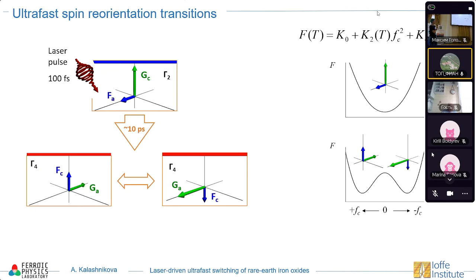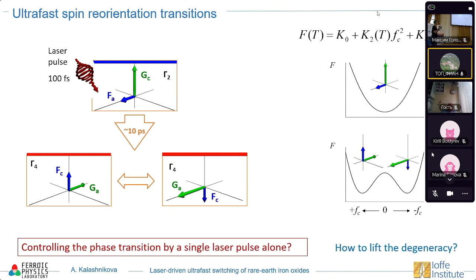So this is the potential energy profile at low temperature and at high temperature. So basically, in experiment, it means that if we take our material and excite it with a femtosecond laser pulse, and we don't have any external magnetic field, we will end up in some kind of a multi-domain state. Can we avoid it? Basically what we tried in our experiments was to find a way to use this delay, this bottleneck, in order to use the other properties of laser pulses to really control the way the magnetization switches during this phase transition.